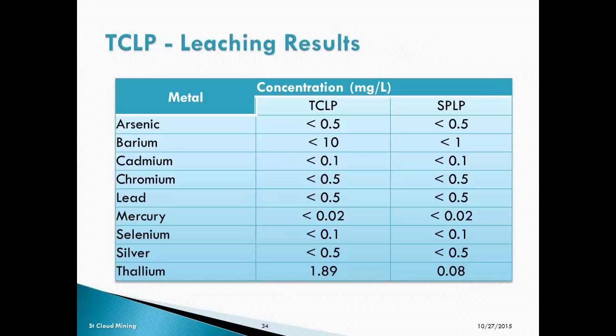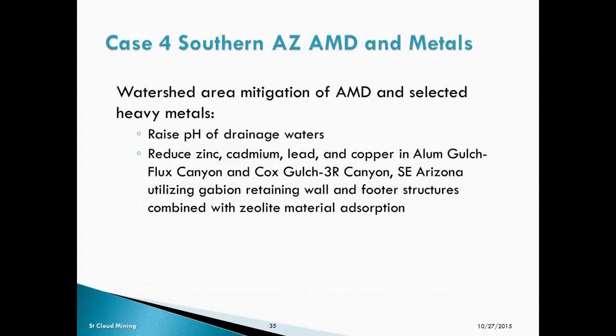The question is, once you've loaded the zeolite on something, what happens? And they did the TCLP tests, and basically what went on to the zeolite stayed on the zeolite. So the zeolite was able to be disposed on site in a lined area for long-term disposal. The final case is in southern Arizona.